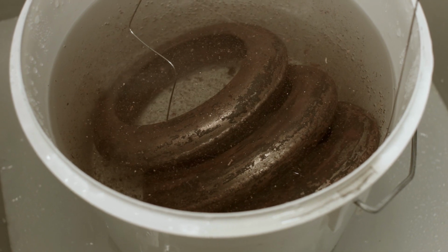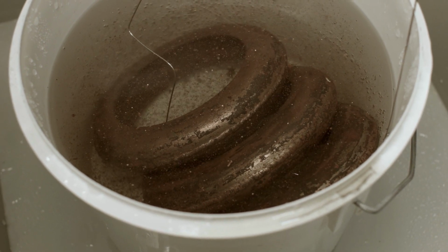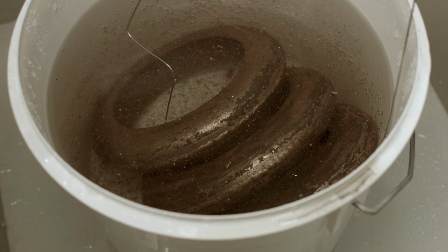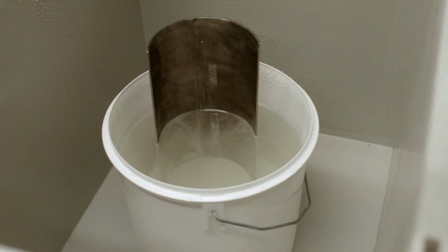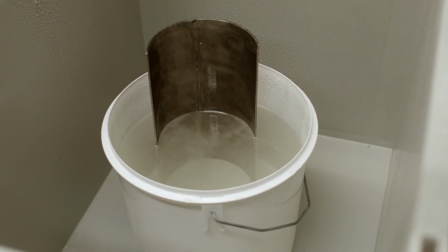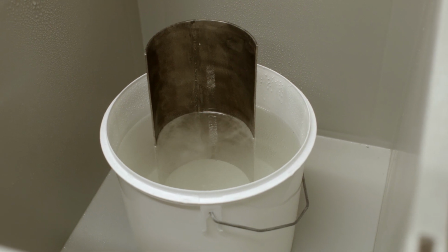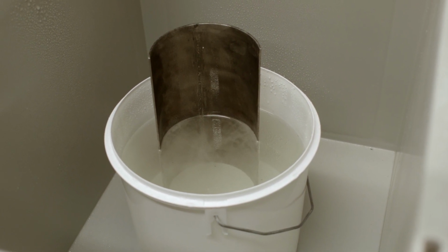To ensure a strong adhesion between the steel and the nickel, the steel must be absolutely clean and oxide-free. Thus, most of the time in the lab is actually spent cleaning the parts. As a first step, the parts are immersed into hydrochloric acid.